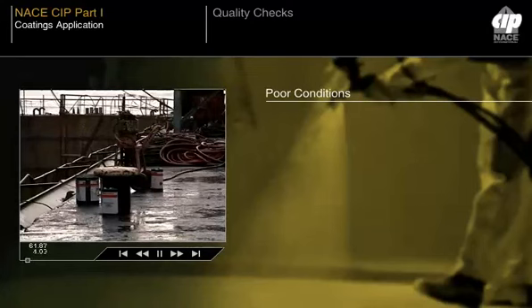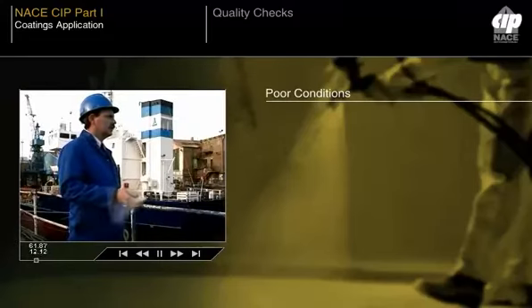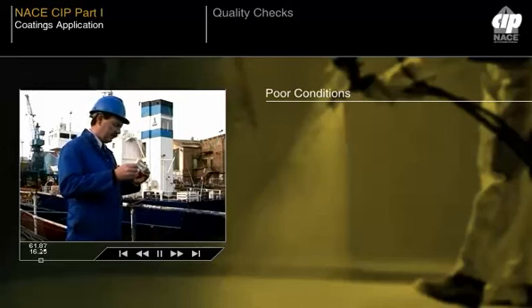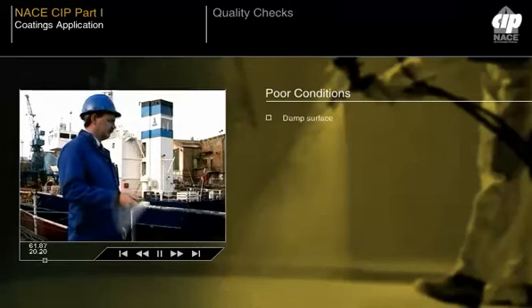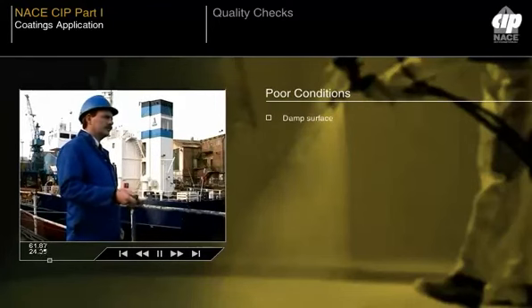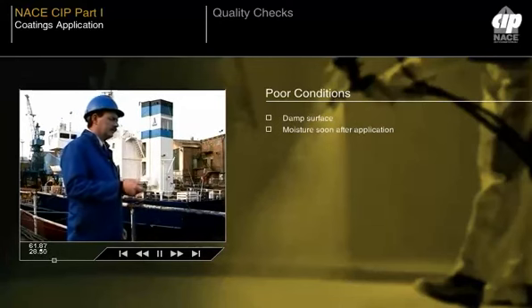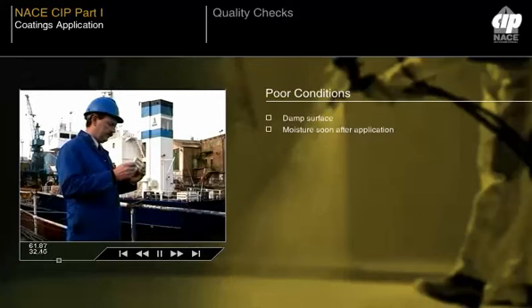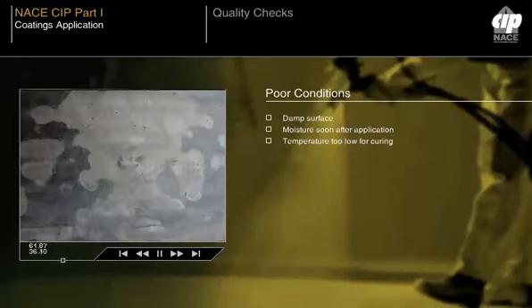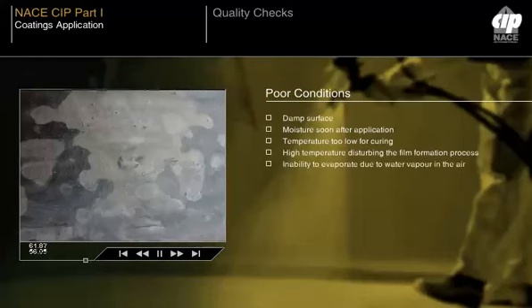Application of coatings during poor weather conditions is likely to result in a lesser quality coating film and reduced protection. Quality control on site should monitor relative humidity, dew point temperature, and the temperature of the surface being coated to avoid problems with coatings being applied to a damp surface, freshly applied coatings becoming affected by moisture soon after application, coatings being applied when the temperature is too low for the curing reaction to proceed, coatings being applied when the surface temperature is too high and the film formation process is disturbed, coating solvents being unable to evaporate due to high partial vapor pressure.